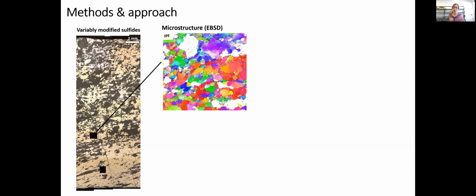Then for both chosen sites, more deformed and less deformed, I map the sulfide microstructure using electron backscatter diffraction, EBSD. Now, I'm sure most of you are familiar with it, but it's an SEM-based analysis that can map out the crystallographic orientations of whatever mineral you're looking at. So in this image, all the colored parts are pyrrhotite, and the different colors represent pyrrhotite grains with different orientations.